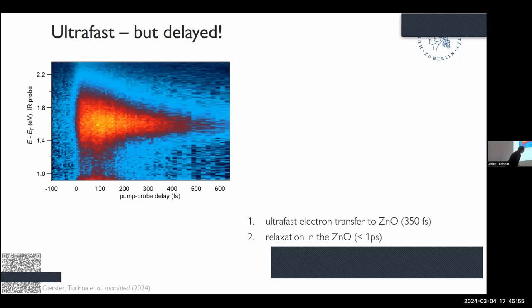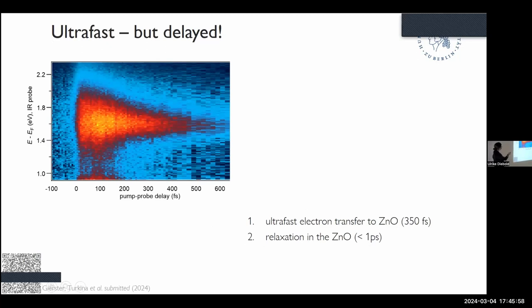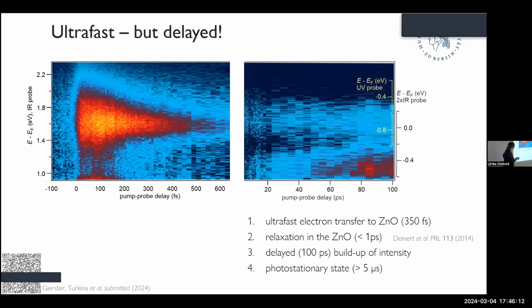Okay, so we've already discussed the population dynamics in the molecule, but we have not looked at what is happening at longer delays. And this is what we see here. On the time scale of 100 picoseconds, a signal builds up again. And this is the signal that I've just shown you in the single spectra. You have a replica depending on whether you probe this photostationary state with UV or IR light, but it's the buildup of this photostationary state.